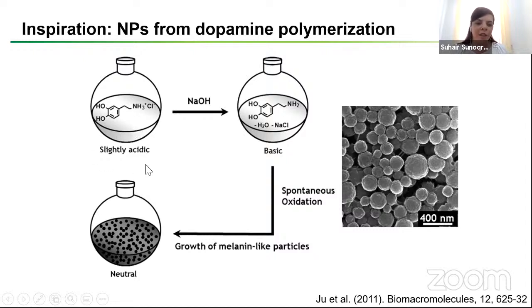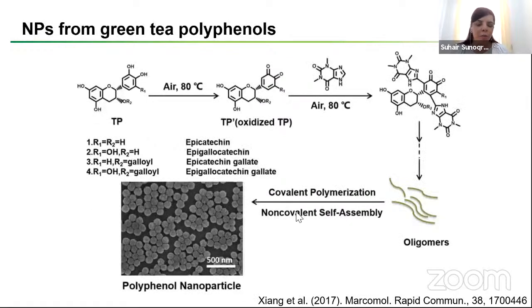So most of the applications were to obtain surface coatings, but the ability to control the reaction so that we can obtain spheres, that's the main challenge. So this was the first hint at the ability of polyphenolic compounds to form nanoparticles. And then another group a few years later reported the formation of nanoparticles from green tea extracts that are rich in polyphenols through a similar mechanism. So basically, as long as you have these catechol OH groups, and they can undergo oxidation under certain conditions, it can react with itself, and you can control it in a way to obtain nanospheres or nanoparticles.